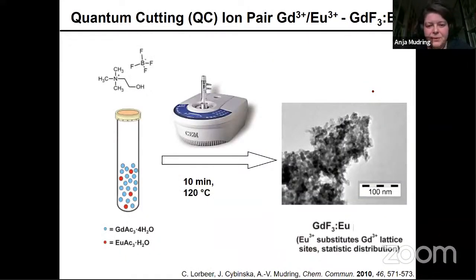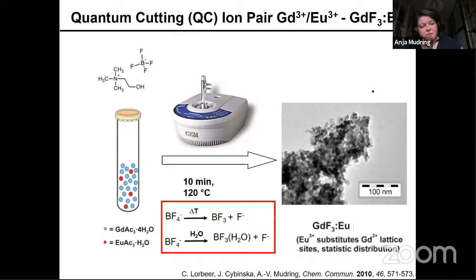And then I remembered the words of my colleague from Imperial College, Tom Welton, who said, you know, BF4 minus containing ionic liquids, they are the antichrists of ionic liquids because they are so unstable and release HF, which is a nuisance for transition metal catalyzed organic reactions when you use them as a reaction medium. But here it's exactly what we want to have. So we took this ionic liquid based on BF4, dissolved gadolinium and europium acetate in it, and then treated it in a microwave. 10 minutes, 120 degrees, like your microwave dinner.